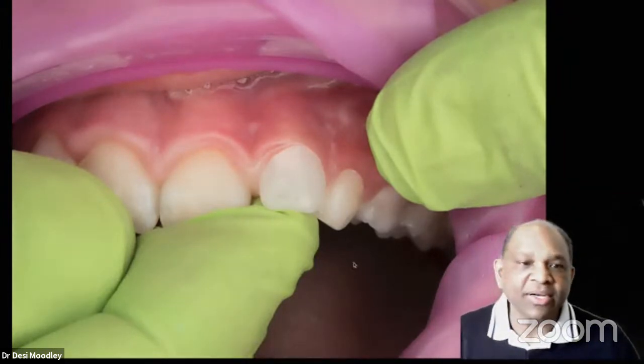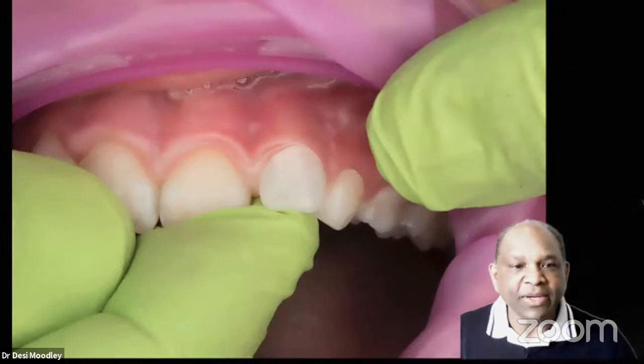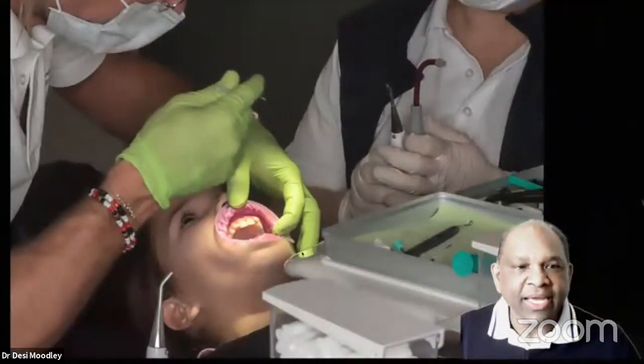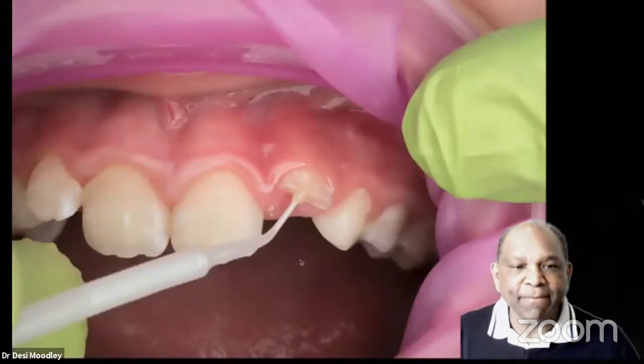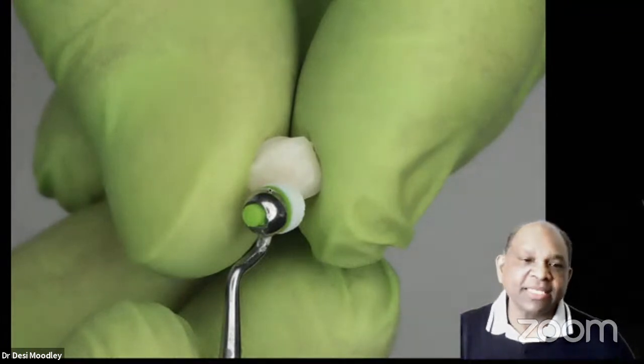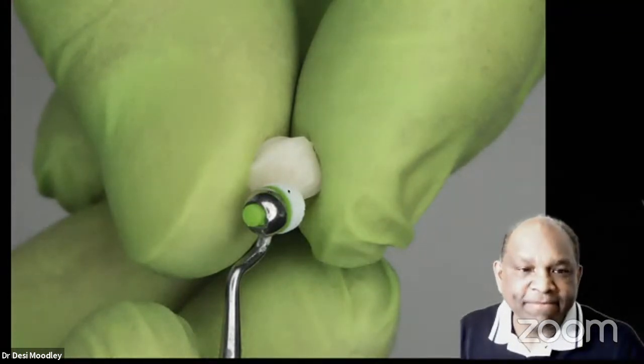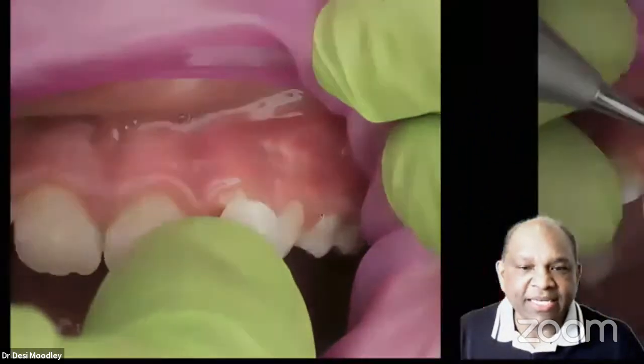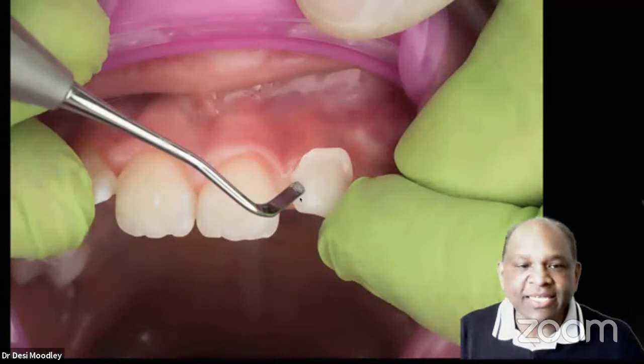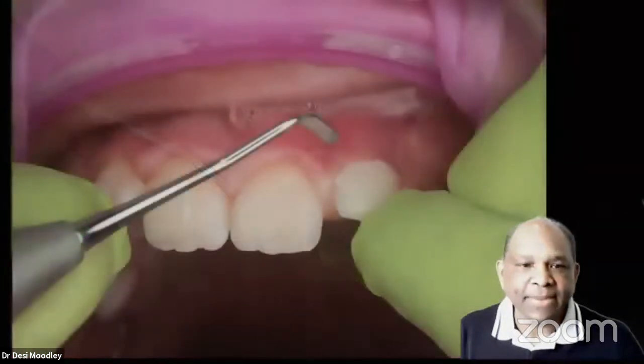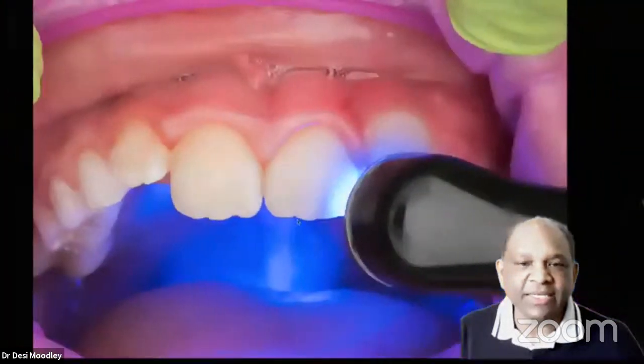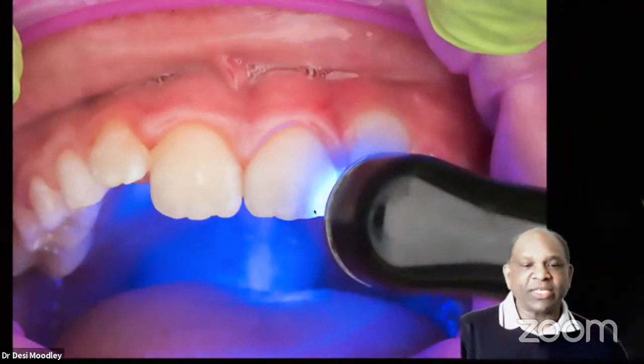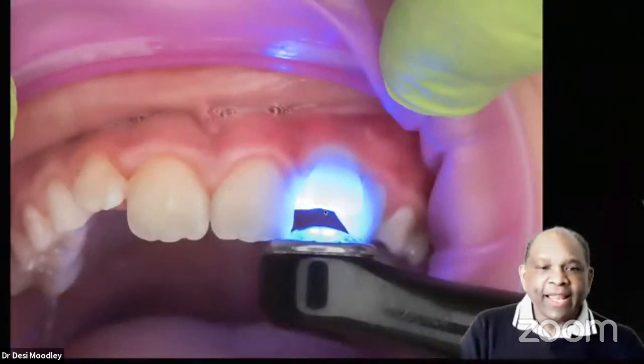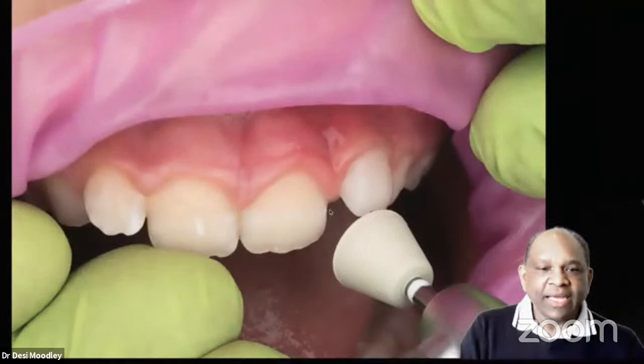So in this case, we stuck supragingival. We prepped the crown, and then we etched and applied our bonding agent. Light cured that, placed some of the Edelweiss composite cement in the crown itself, and then placed that in the mouth, and then removed any excess. Remove all excess material, then light cure that in all directions for 20 seconds in each direction. That's light curing. And then final adjustment.